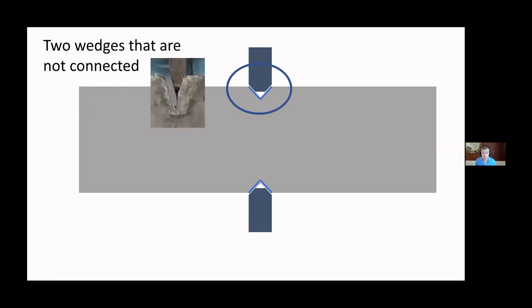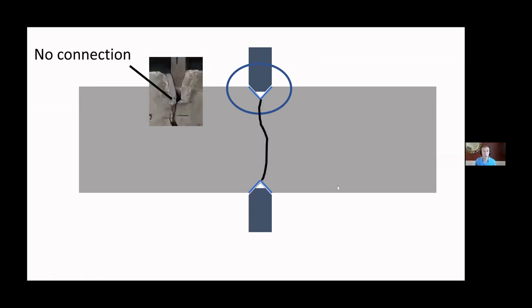We've actually developed a test to evaluate this. We call it the split beam test. You take a beam and you cast some steel wedges in it. You take a platen and you load it from the top and the bottom. And these wedges are important. They're not connected at the bottom, so they can move back and forth from one another. So as you push down from the top and the bottom, crack.